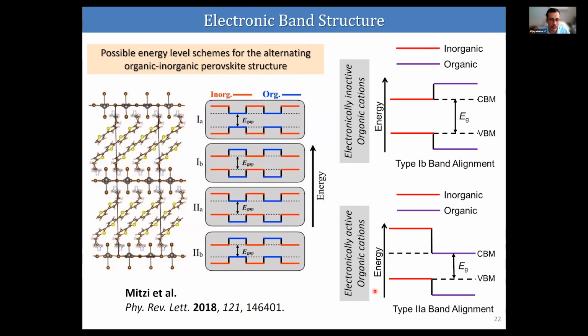from the organic cations also, because the studies by Mitzi revealed that there is a possibility of 4 kinds of band structure. One is the type 1A, where the organic components are contributing to both the conduction band and the valence band maximum. The other one is the type 1B, where the inorganic structures are contributing to both the conduction band and the valence band of the material. And normally most of the perovskite comes to this class, that is the type 1B band structure. And type 2A, here the organic is contributing to the conduction band minimum, and the inorganic moiety is contributing to the valence band maximum, and vice versa is happening in the type 2B.